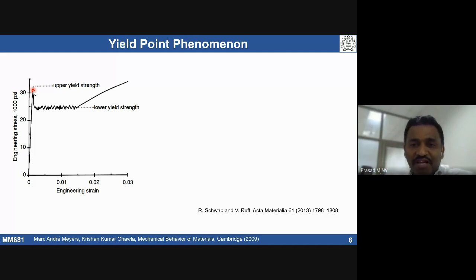So that dislocation density, rho, has some stress field. It has a stress field - the dislocation core has some field. So what happens? These solutes can interact with those stress fields and can form an atmosphere.